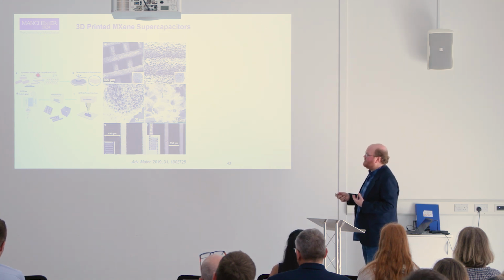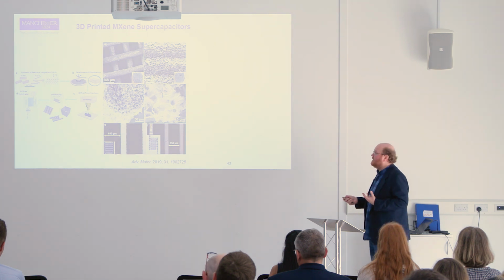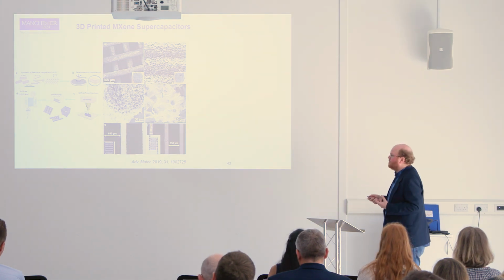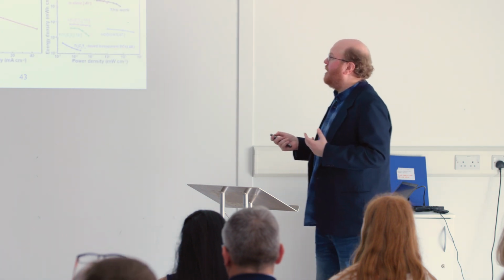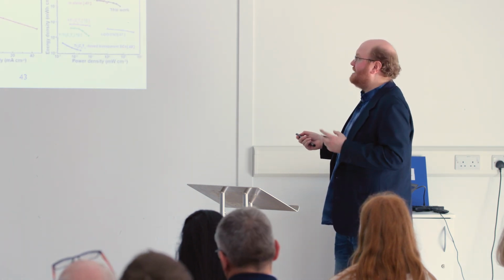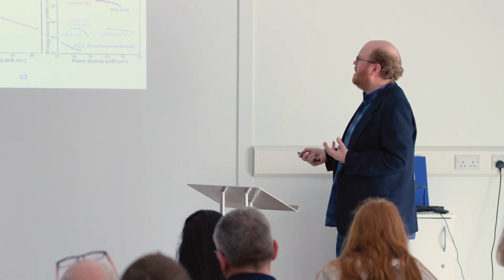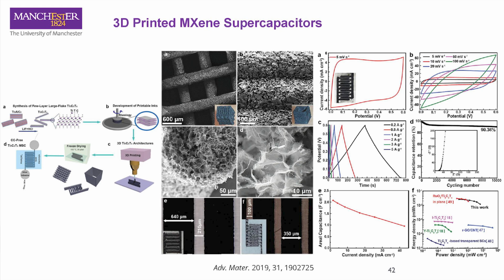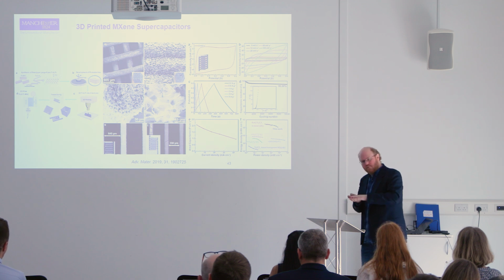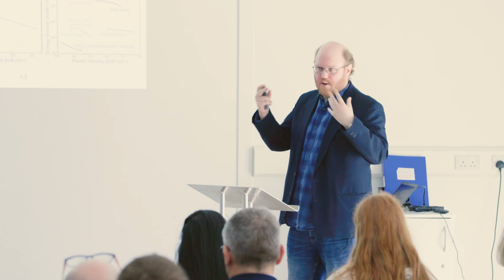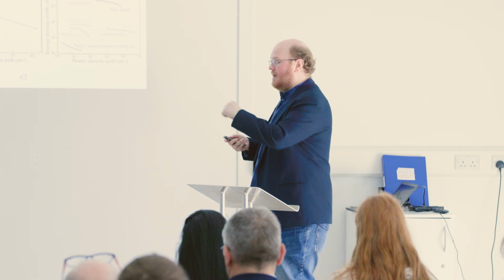So in this work, we were taking these MXenes, exfoliating them, and 3D printing them into these structures, and then freeze drying them to remove the solvent, getting a very, very high surface area aerogel structure, which is really good for supercapacitors and energy storage applications. You can see here that we're getting a very ideal sort of structure, so there's no pseudocapacitance, it's very stable, and the capacitance is much higher than, say, pure graphene material, but if you start looking at composites of these, you can get added benefits as well. So 3D printing is one of the ways to rethink this. We said the problem with energy storage is when you make a coating of these, you restack them, and that ruins their properties. 3D printing and aerogels is a way to prevent that restacking through the way that we make the composite structure.